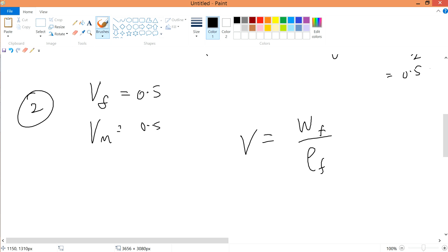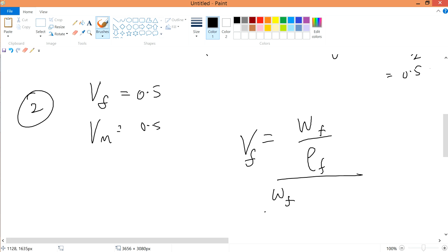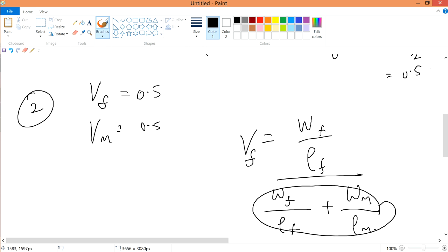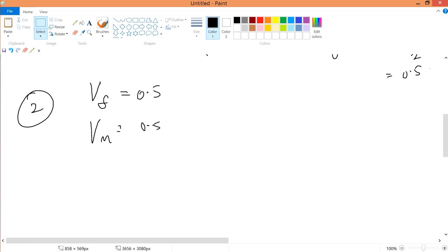So there is a ratio between the fiber and the matrix, your fiber and your resin, because your whole composite includes your matrix and your fibers together. So the volume fraction is the ratio between your fiber and your whole composite, and therefore you're going to include your fiber volume plus the volume of your matrix. So this is the whole composite, 100%. This is only the fraction of the fiber. If you take the ratio of it, you'll get your volume fraction of your fiber, and this will make sense and you can remember it more clearly, hopefully.